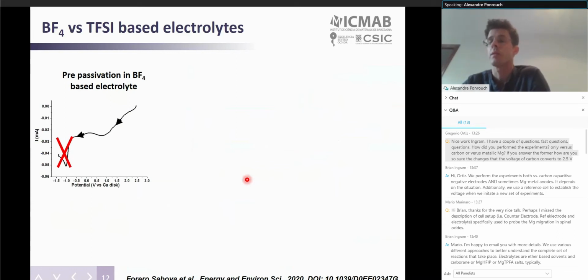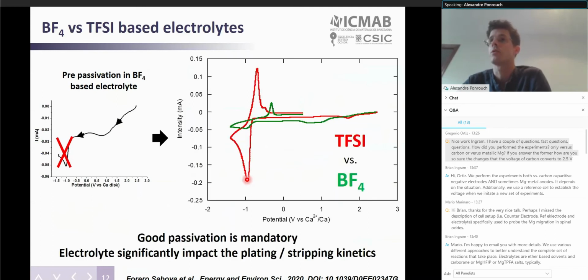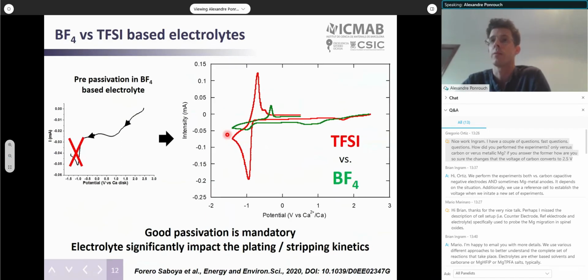We pre-passivated two stainless steel discs in calcium BF4 based electrolyte, forming this borate containing passivation layer on the two discs, which we then rinsed carefully and transferred to a BF4 or a TFSI containing electrolyte. Here you can see the new cyclic voltammogram that we obtained in these two electrolytes that we tested before.